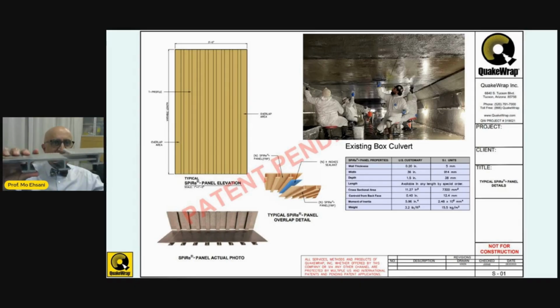But we put that sealant in between these, and then in this case, because the length of this repair of that culvert in Phoenix was 380 foot long, you divide that by 3 feet, and you see that you need maybe about 130 or so panels of 3 foot wide to cover the whole length of that. Okay, so it would have been much easier. Of course, it does take a little, because this is 1.5 inch or 38 millimeter thick. So we mount that with a little bit of a gap between.